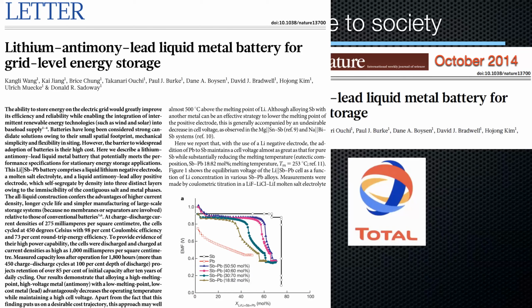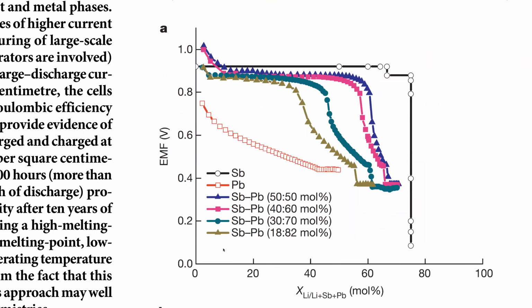And as you know, lead melts at 327 degrees Celsius. But lithium lead is a low voltage. So you can see in this graph here, I think I can show you in the next one. So this red curve is lithium lead. And this blue curve at the top is lithium antimony. So if we added lead to antimony, the melting point would come down. But we figured that the voltage would come down as well. There would be somewhere in between.